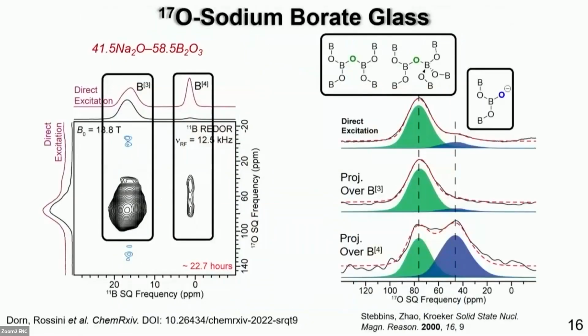So the first system that we looked at was this oxygen-labeled sodium borate glass that was made by Dr. Alexander Patterson. So this 2D experiment was recorded at 18.8 Tesla in just under 1 day. And we estimate that this oxygen labeling is around 20%. So what we can see is we can clearly resolve the 3 and the 4 oxide.